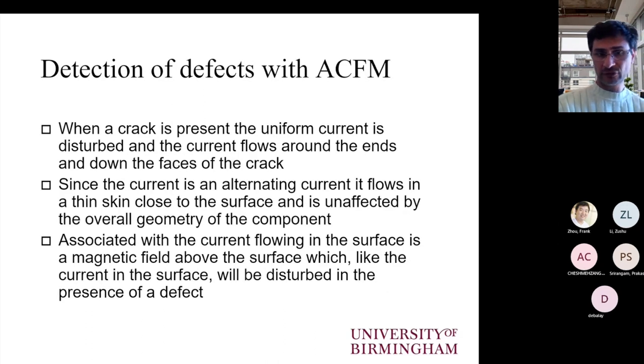Now, we already mentioned this, so when a crack is present, the uniform current field will be distorted, and some of the lines will deviate from the sides, and other current lines will dive deeper and go below the crack. So this will give rise to changes in the corresponding electromagnetic field, both in the Z component and in the X component, because the flux is a vector quantity and it's three-dimensional. So we have X, Z, and Y orientations that are of interest.